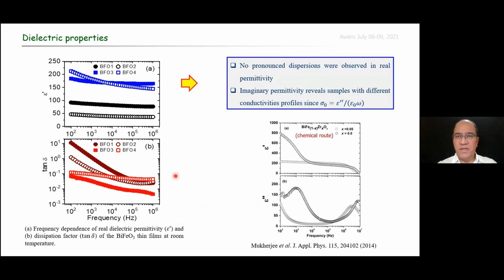Regarding the dielectric properties, no pronounced dispersions were observed in the real permittivity, as we can see in this figure A. And no dielectric relaxations were observed in our films, as sometimes observed in the literature, as summarized in this figure for a BFO film prepared by a chemical route. In this case, the dielectric relaxation could be suppressed by introducing 5% of zirconium. In our case, at room temperature, this dielectric relaxation was not observed in principle. Another important result in this figure is that the imaginary permittivity reveals samples with different conductivity profiles.